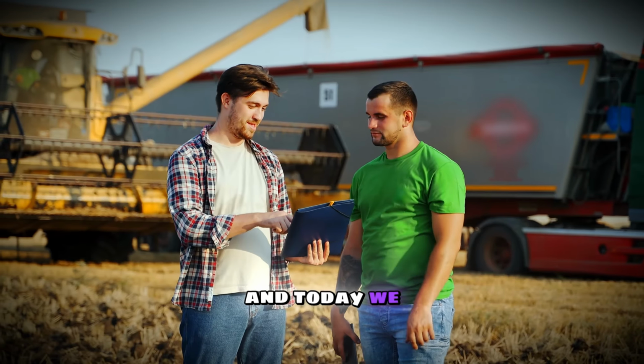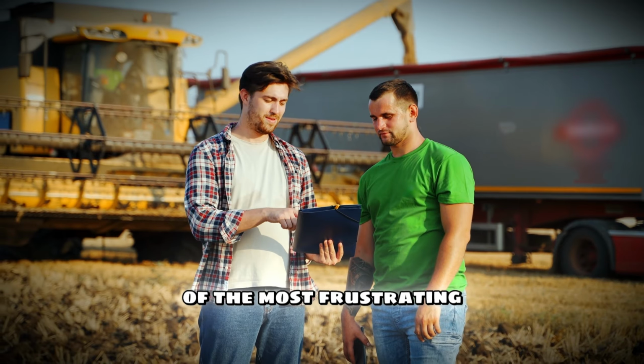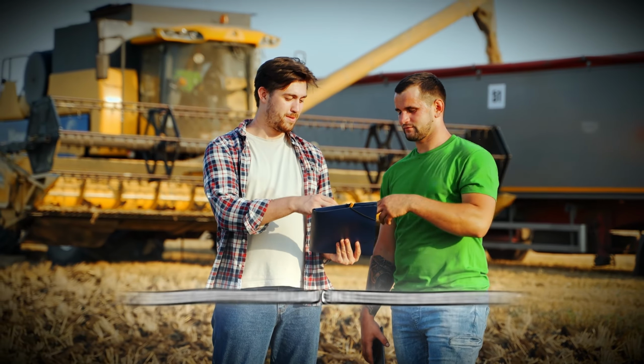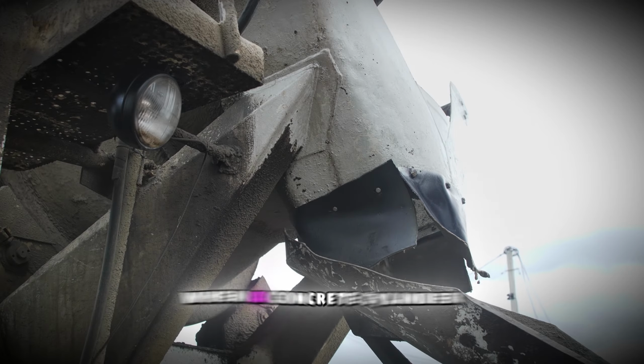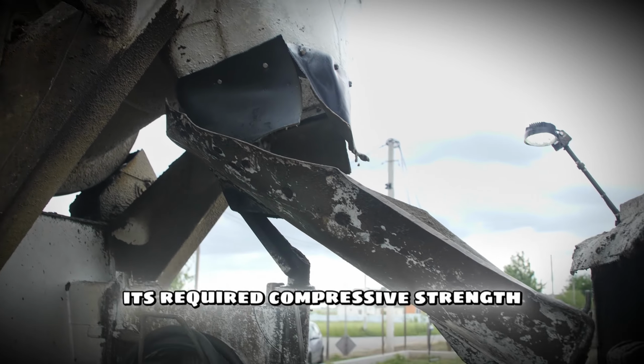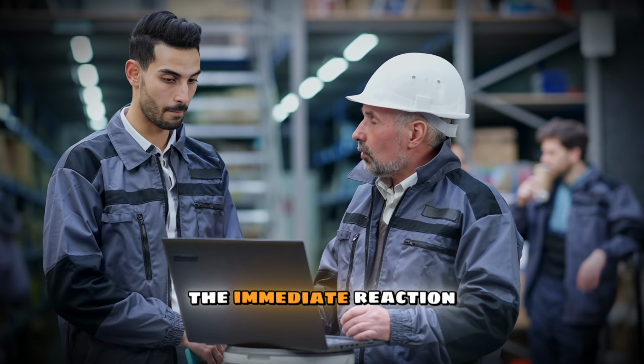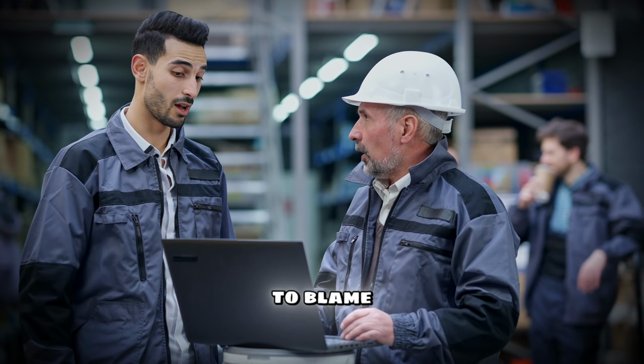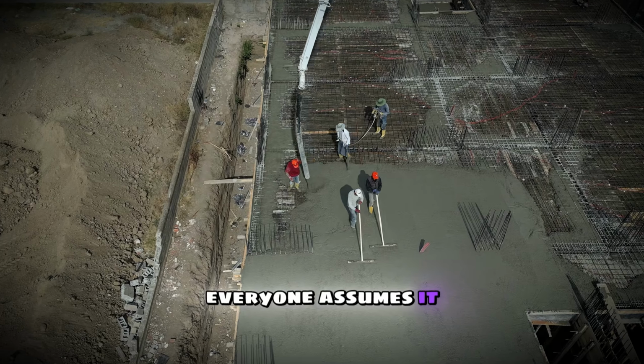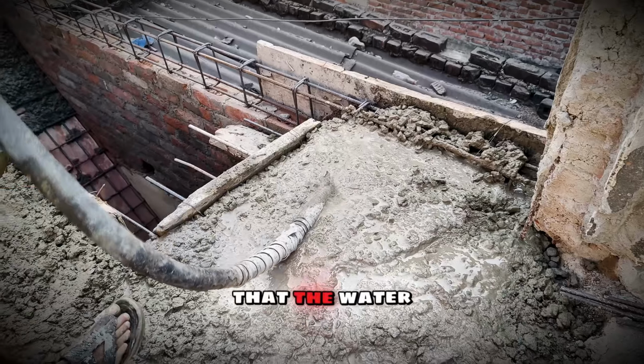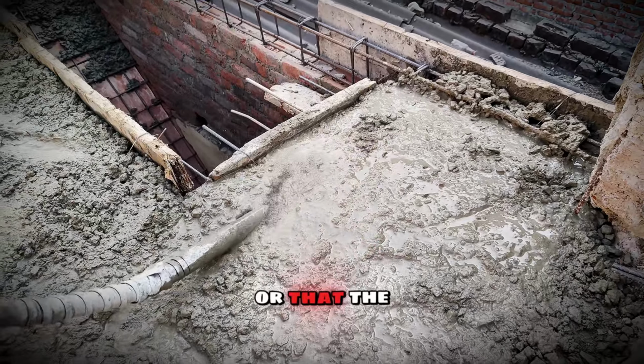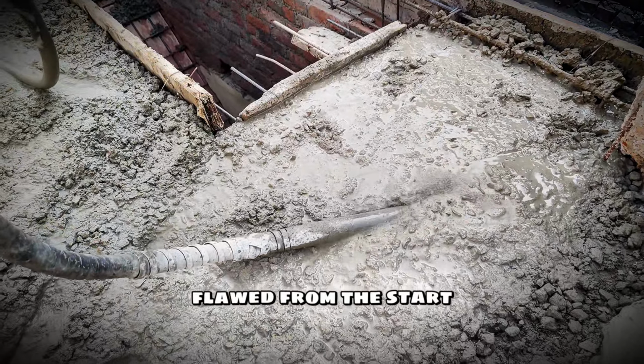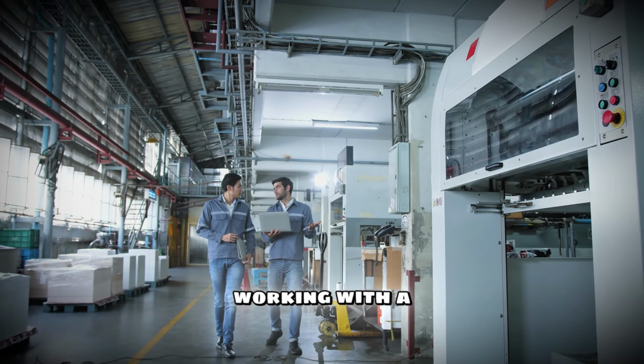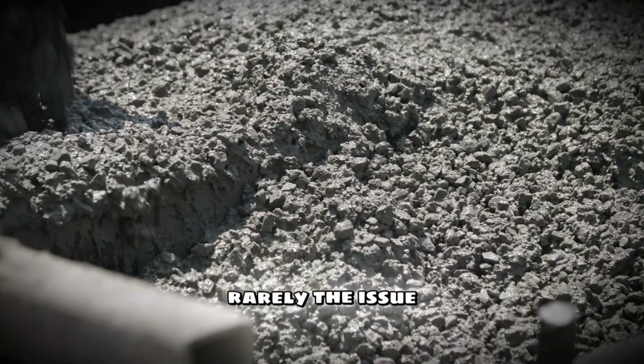Today we are tackling one of the most frustrating, headache-inducing problems in the construction and concrete industry, the dreaded bad break. When a concrete cylinder fails to meet its required compressive strength at the 7-day or 28-day mark, the immediate reaction is almost always to blame the ready-mix supplier. Everyone assumes it was a bad batch of concrete, that the water-to-cement ratio was off, or that the mix design was flawed from the start. But in reality, if you are working with a reputable supplier, the mix is rarely the issue.